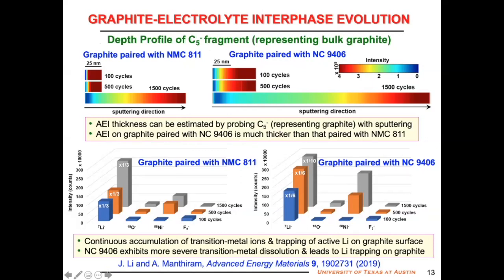This slide is important. We are comparing the SEI thickness on the graphite. The only difference is, in one case 811 cathode, another case NC 9406 cathode. Everything else is the same. By sputtering, we see how much depth we have to go to see the graphite as a function of cycle number. 811, after 1500 cycles, you have to sputter this much to see the graphite. NC 9406, you have to sputter that much to see the graphite. The scale bar is here, so you can compare. That means the graphite has a much thicker SEI layer when it is paired with 94% compared to 811. Only the cathode is different. Anode is the same, everything else is the same.